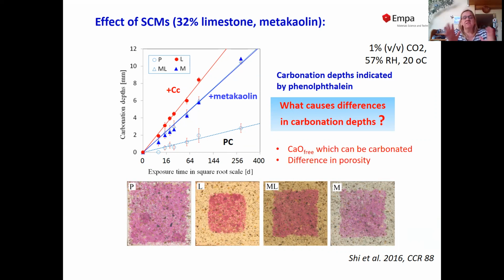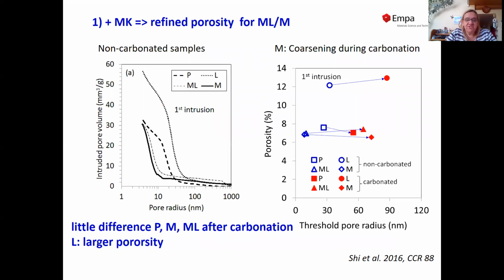There are two main effects, as we know from literature. It's the amount of calcium oxide available to be carbonated, and the second effect is the porosity. If we start first with the porosity, we can see that the limestone sample here, with L, has the biggest pores, the highest total porosity, as well as the biggest pore parameter, while the Portland cement sample has somewhat less porosity and also smaller pore size. The metakaolin samples have an even smaller pore size and less total porosity. So we think that's one of the main reasons why we have this somewhat slower progress of carbonation we've seen for the metakaolin containing samples.